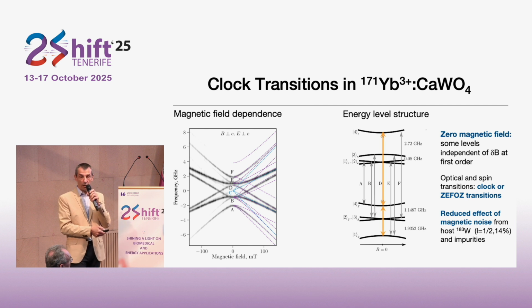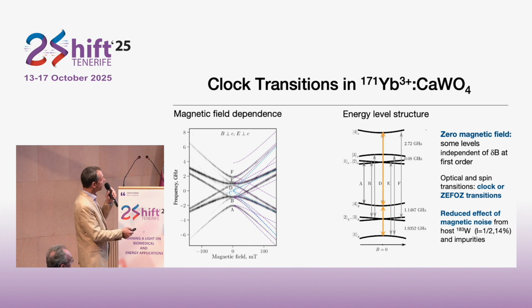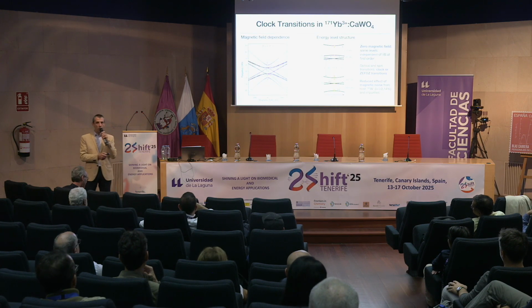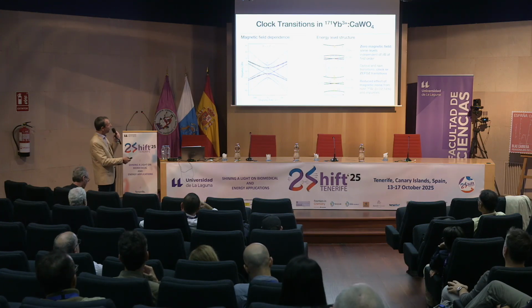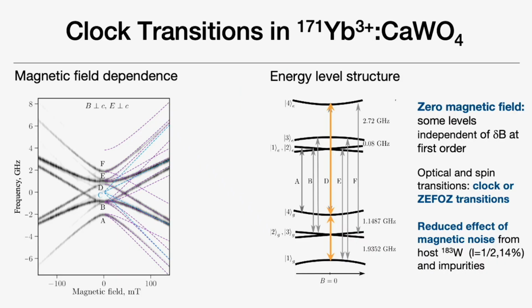As you can see, some levels have a horizontal curve, right? Horizontal shape. And so this means that the energy of this level, for example, does not vary so much, or even does not vary at all at first order when you have small magnetic field fluctuations. So this is why you have this flat shape here. This is also true for this level. However, here it's not true. Here you can see that you have a linear dependence with the magnetic field. But again, for these two levels here, you also have this property that at first order magnetic field fluctuations have no effect on the energy of the level.